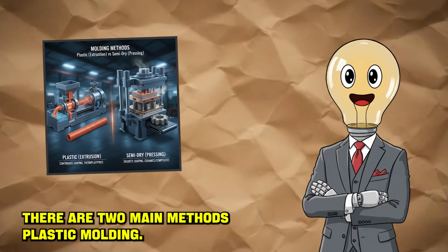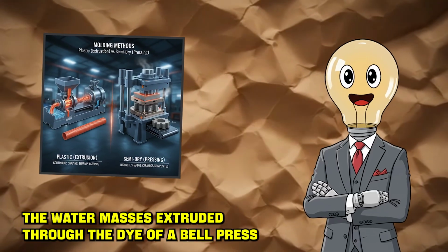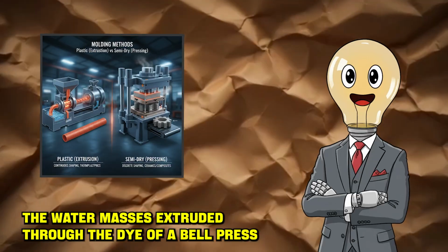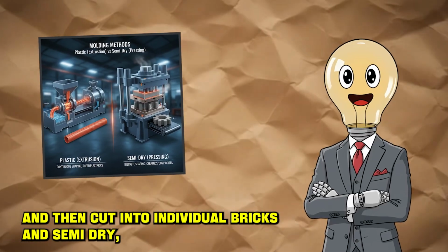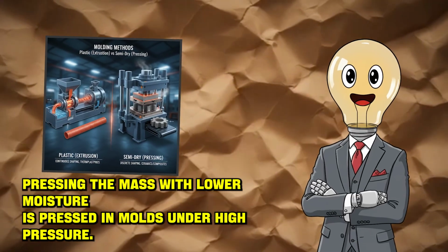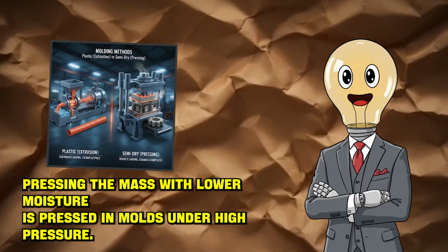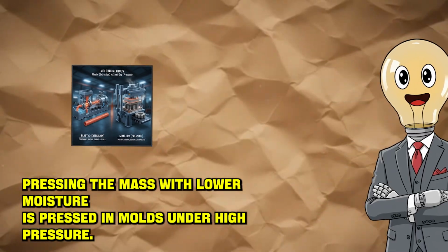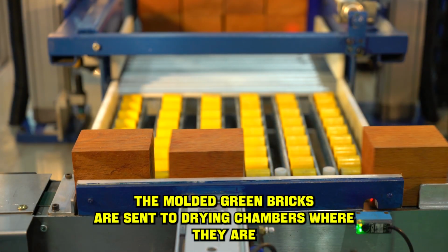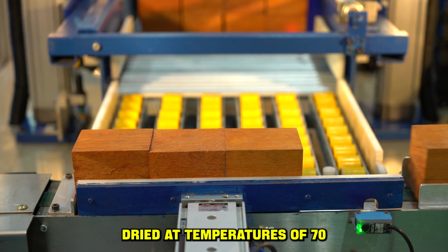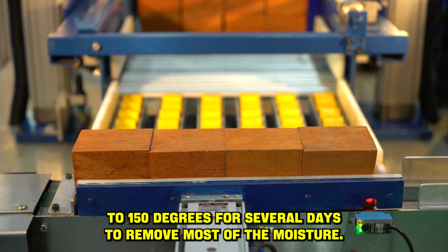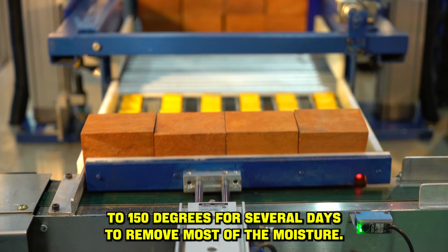There are two main methods: plastic molding. The wetter mass is extruded through the die of a belt press and then cut into individual bricks, and semi-dry pressing. The mass with lower moisture is pressed in molds under high pressure. The molded green bricks are sent to drying chambers where they are dried at temperatures of 70 to 150 degrees for several days to remove most of the moisture.